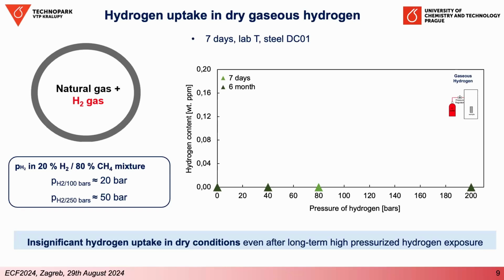So now let's move to a purer source of hydrogen. We use in our labs just pure hydrogen, but we are following the mostly discussed mixture with natural gas, 20% of hydrogen. So the total pressure of our pure hydrogen is correlated with the partial pressure in this discussed mixture. And as you can see, we are not able to measure hydrogen entry even after 6 months of exposure, at a somewhat higher hydrogen pressure, to be really on the conservative side. I have to express here that these are just bare sheets, and this mechanism isn't really happening much here.